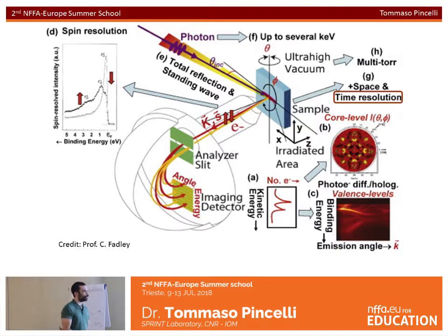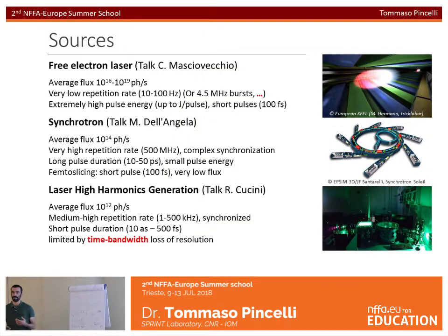What are the sources that we can use to perform photoelectron spectroscopy? We need sources of pulsed X-ray photons, so the amount of pulsed sources is limited. So we have the free electron lasers, which will be described in a talk by Claudio Masciovecchio. These kinds of sources have a very high photon flux, the average photon flux, that is achieved though by a very low repetition rate and a very high amount of photons per pulse in short pulses. So we will see that this is not the easiest way to deliver light for photoemission.